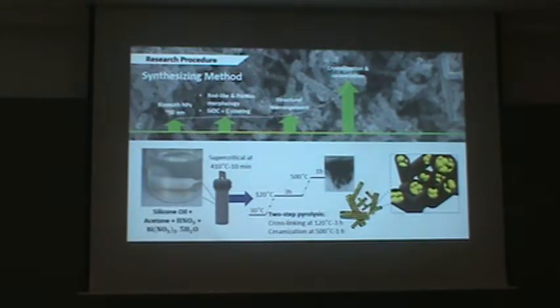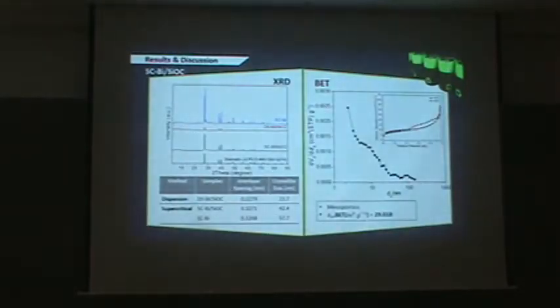Here is the research procedure. We did a simple method by mixing the precursor, bismuth nitrate pentahydrate, in acetone with nitric acid, followed by homogeneous mixing with silicone oil. Supercritical treatment is then done for 10 minutes, followed by a two-step pyrolysis at 120 degrees and 500 degrees. This is to allow for structural rearrangement and also for crystallization.